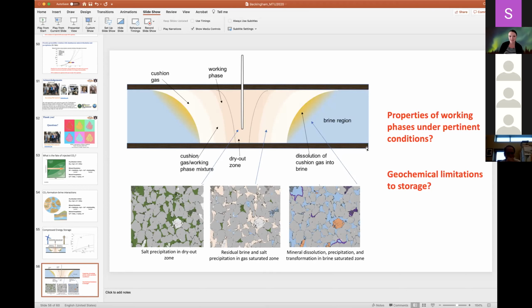Aren't these secondary minerals, when they precipitate, often amorphous? Aren't they clogging up your pores? We could have some amorphous phases. Actually, we looked at the potential for amorphous silica to precipitate with our CO2 simulations, and it was not thermodynamically favorable. Quartz was thermodynamically favorable, which was surprising to me. I was expecting amorphous silica.